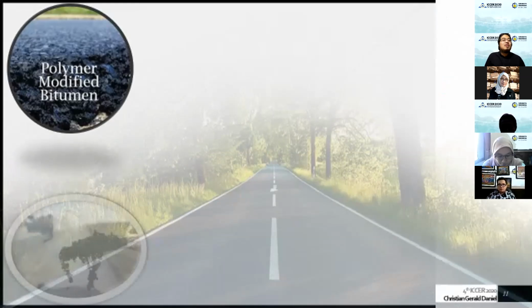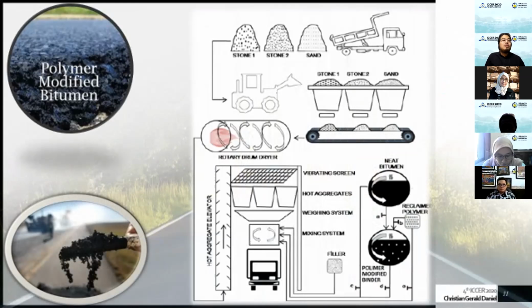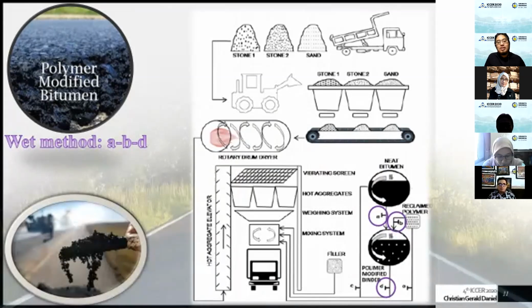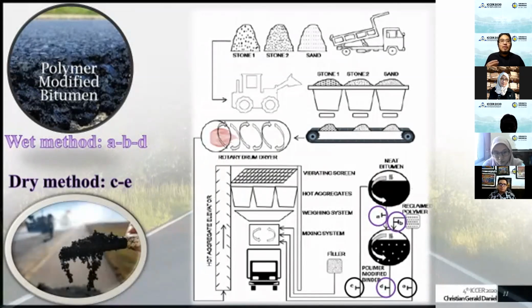With the wet method, basically we will create the polymer modified bitumen, or PMB, whereas using the dry method, we could create either a fiber reinforced mixture, or we could substitute the aggregate partially. This is the schematic. For the wet method, basically we have A, B, and D, which means that the neat bitumen will be mixed with reclaimed polymer, and then the modified bitumen will be mixed with aggregate. Whereas in the dry method, both are mixed simultaneously, so not the bitumen mixed with polymer first.